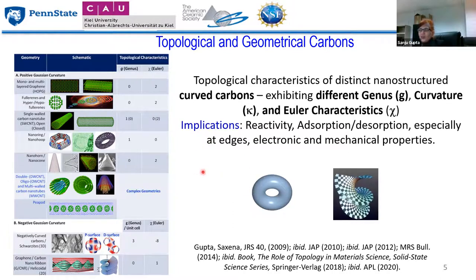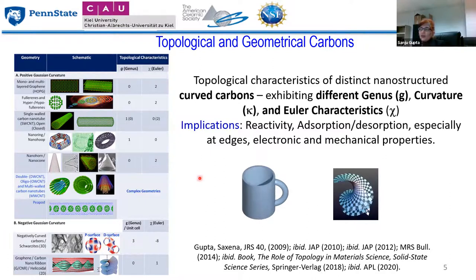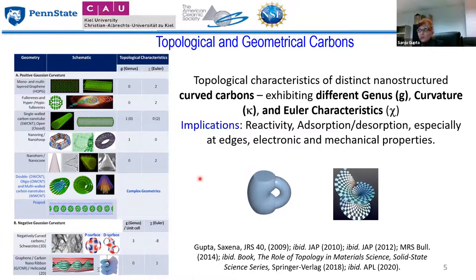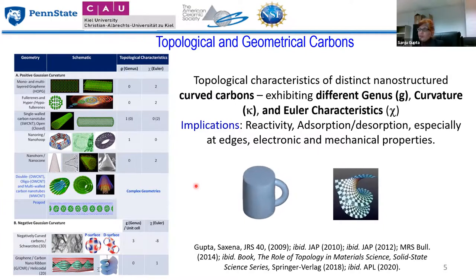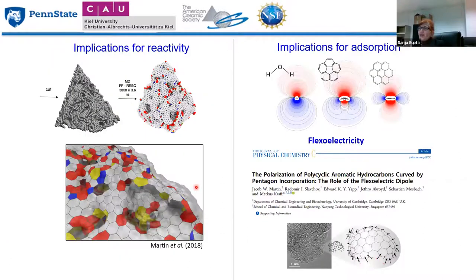But experimentally they are showing implications in higher reactivity or electrochemical activity, higher adsorption and desorption capacity, especially at the edges, because these are what we call topologically protective sites, and also some implications for the electronic and mechanical properties. And that's basically what I was talking about, that they have implications for both, which are directly relevant for the applications that I have studied.